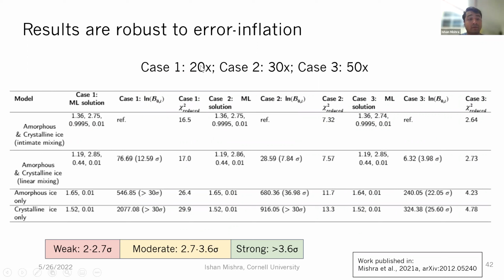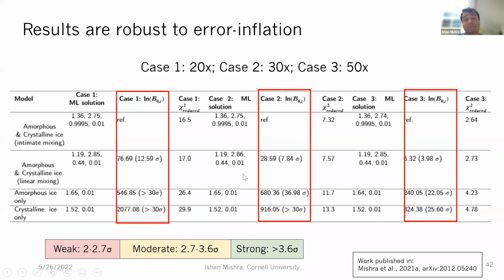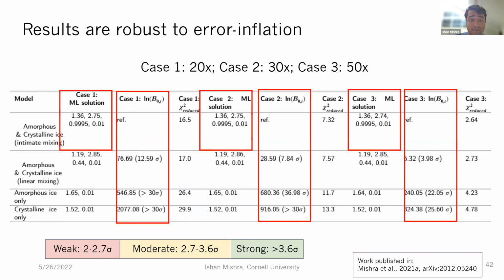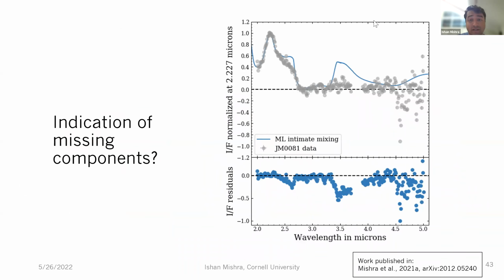We tried a range of inflation parameters consistent with how much this difference is, and our results were pretty consistent. The intimately mixed model was preferred for all cases, and the maximum likelihood solutions were also pretty much the same. So that was good: even though we were probably working with underestimated errors, it was fine within our idea of the factor of underestimation. And of course, as I pointed out, there were regions where the model was just not fitting the data well.